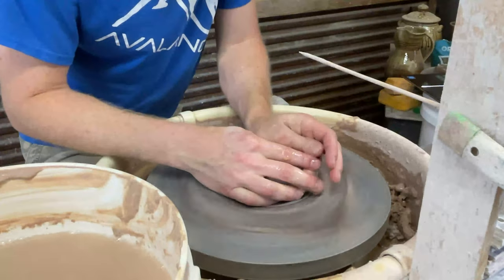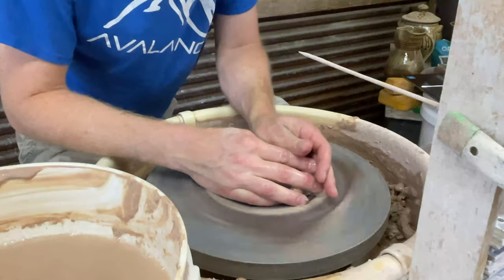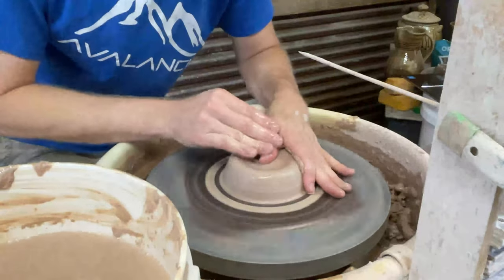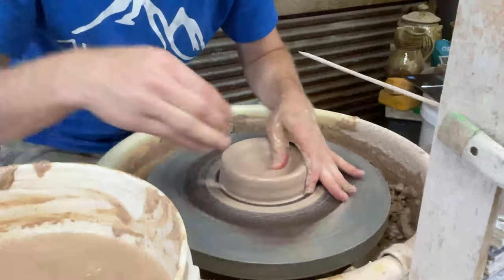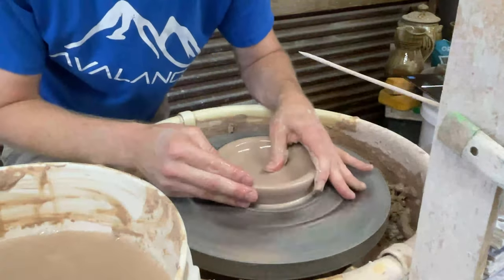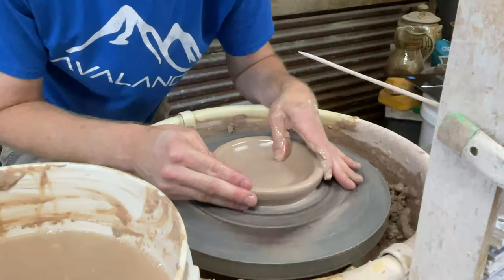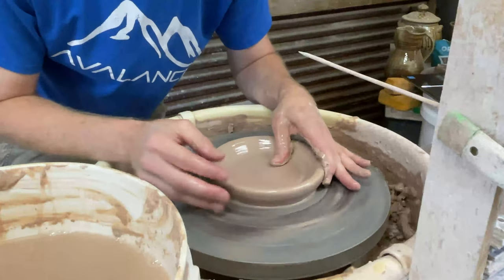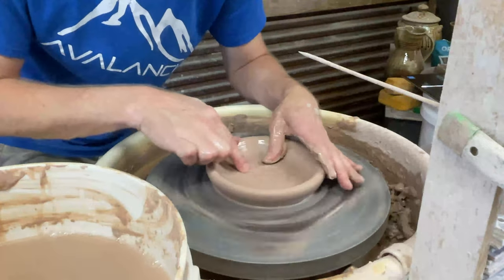Christina, am I wood firing to cone 10? It goes a little bit hotter than that. I get the back of the kiln, which is the cooler part in my wood kiln, gets to cone 11 is down, and 12 is usually soft is what I want. The front, 13 is pretty much down, but it's still visible as far as you can see underneath it.